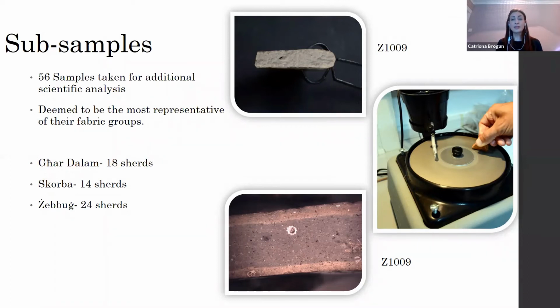samples that we took were deemed to be the most representative of the different fabrics present within each of the 3 phases. So it's not 18 individual fabrics; we basically tried to get at least 3 sherds of the same fabric for each fabric type, just so that we had a bit of comparison between sherds. The subsamples were then subjected to various types of analysis, but essentially all of the analysis was concerned with identifying the components from which the sherds were made, so that we can then see if the fabric groups identified were real or if there were new classifications, new fabric groups.